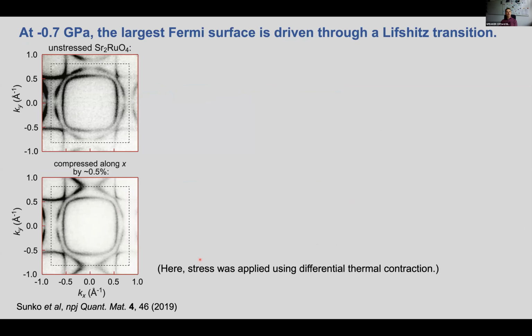Under uniaxial stress, we achieve a Lifshitz transition in a different way. As I told you before, the gamma sheet distorts elliptically and eventually touches the Brillouin zone boundary here. So this is ARPES work, first on unstressed strontium ruthenate at the top, and then coming down, this is photoemission data on a sample that has been compressed along the x direction by about 0.5%. This was done using differential thermal contraction.